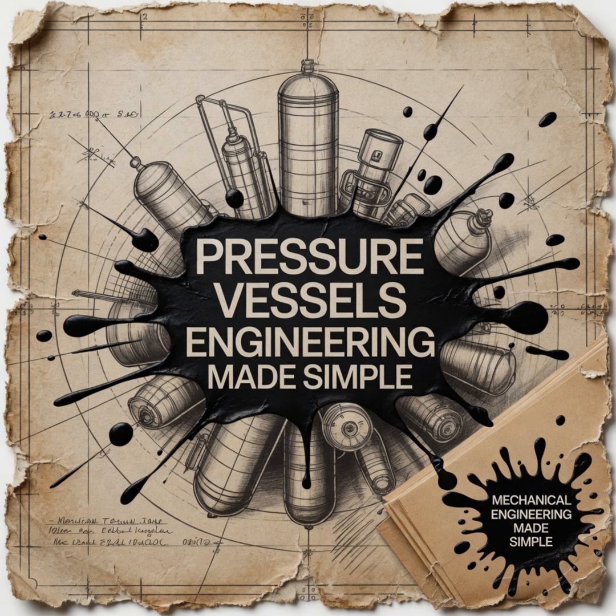Precisely. I read about how they actually verify the metallurgy of these production welds, and this is where it gets really intense. Oh, the test plates. Yeah. They don't just rely on the initial PQR. For high-stakes vessels, they use production test plates. Right. They literally tack an extra piece of steel plate onto the end of the vessel seam, run the welding machine right through the vessel joint and out onto the test plate, cut the plate off, and send it to a metallurgical lab to be destroyed.